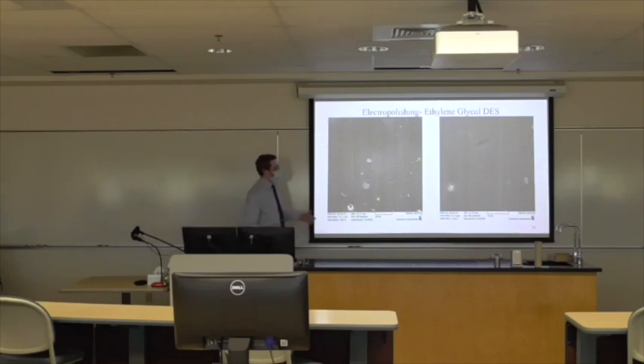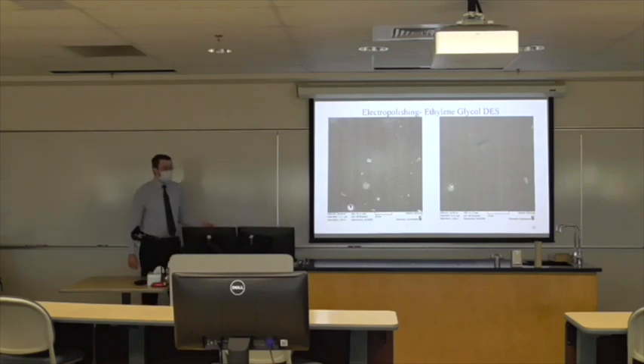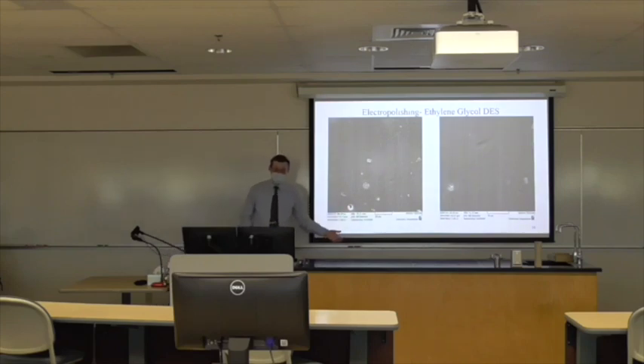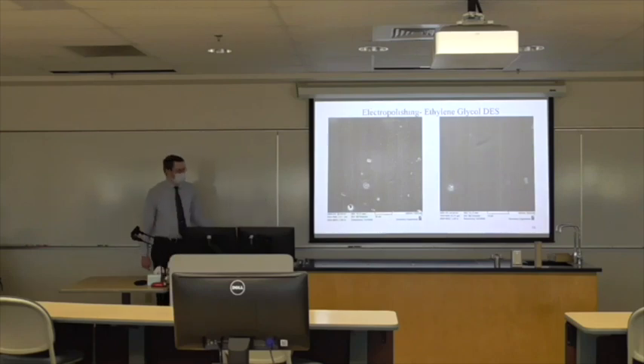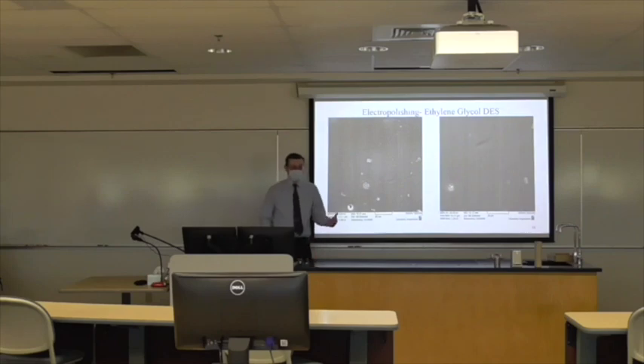However, one of the issues is that ethylene glycol is not environmentally great. Still better than, say, chromic acid or chloric acid, things of that nature, but still not good, which is why the ethylene glycol that we use in our antifreeze, we're trying to move away from to other sources and just use less in general. So we decided to try using a slightly different DES. In this case, we switched the ethylene glycol with propylene glycol. Propylene glycol, which you'll find in your food if you read the ingredients, is a pretty common food additive, combined with choline chloride. Choline chloride is a pretty common additive, as well as in things like chicken feed. So very common materials. Now, for the choline chloride propylene glycol DES, published information indicates it works at a 1:2 ratio.